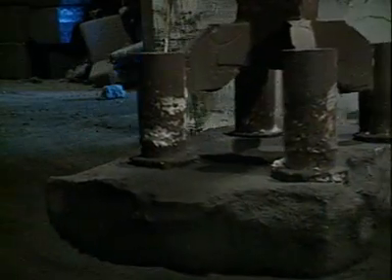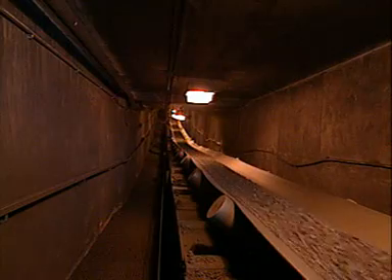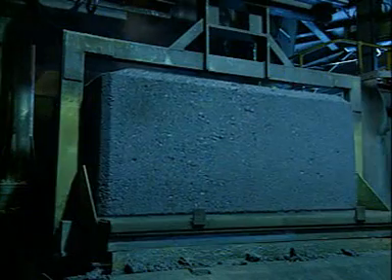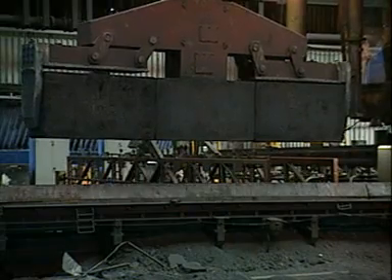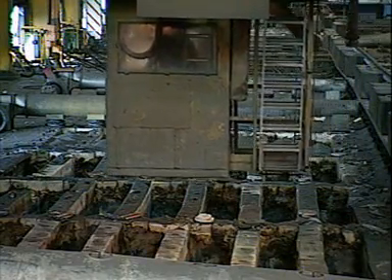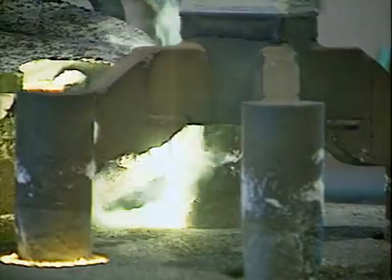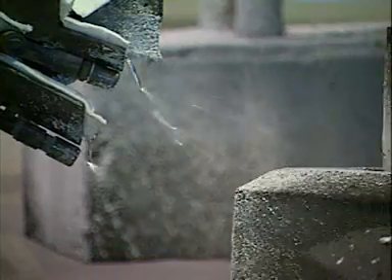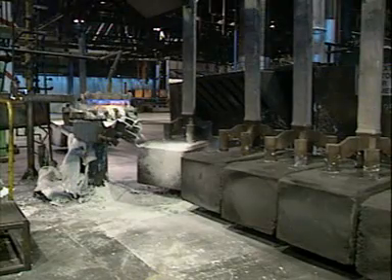The remaining carbon is broken off the old anodes, crushed, mixed with new coke and pitch, and pressed into shape. The newly pressed anodes are baked for about 24 hours in gas-heated pits. Steel stubs are fitted onto the baked anodes. The anodes are then sprayed with molten aluminium to protect the top and sides.